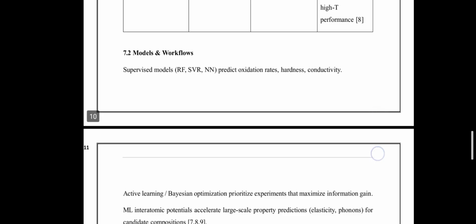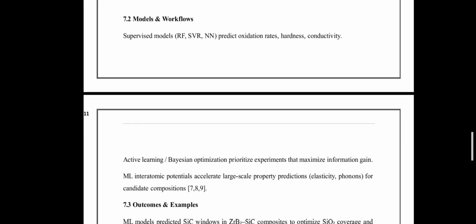Now we will move toward the models and the workflows. Supervised machine learning models such as random forest (RF), support vector regression (SVR), and neural networks are widely used to predict oxidation rate, hardness, and thermal and electrical conductivities. Active learning and Bayesian optimization prioritize experiments that maximize information gain, reducing the number of costly high temperature syntheses. ML interatomic potentials accelerate large scale property prediction, such as elasticity and phonons for candidate compositions, far beyond what DFT alone can achieve.